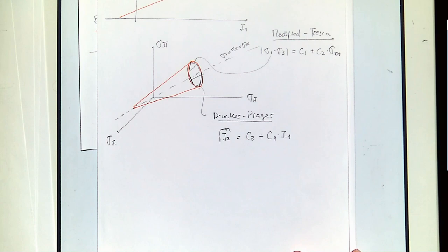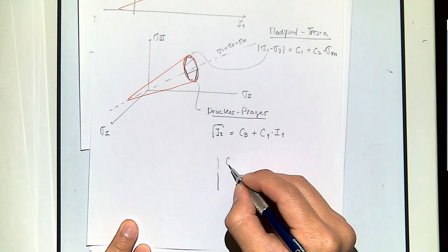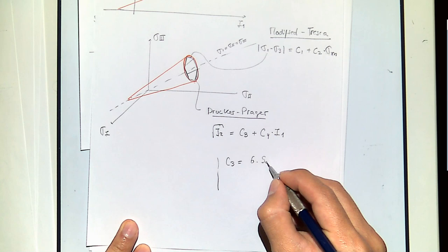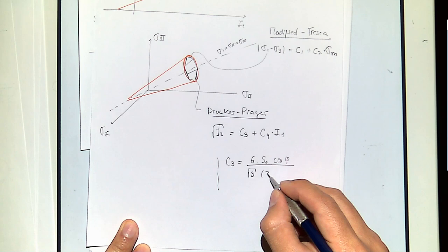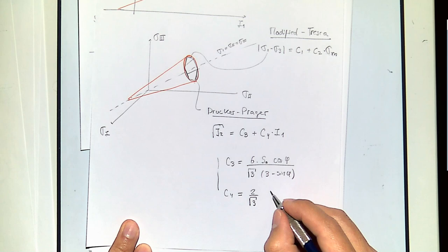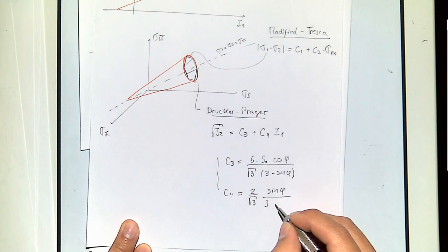And just to complete the picture here, if you were to use a friction angle in this Drucker-Prager criterion, C3 would be equal to 6 times, and we're going to see what these parameters mean, S0 and cosine of phi. But let me write it now so I don't have to come back and write it again later. And C4 is going to be another constant, which also depends on the friction angle. Well, it's the sine of phi over the square root of 3 times 3 minus sine of phi. All right, so C4 just depends on the friction angle,